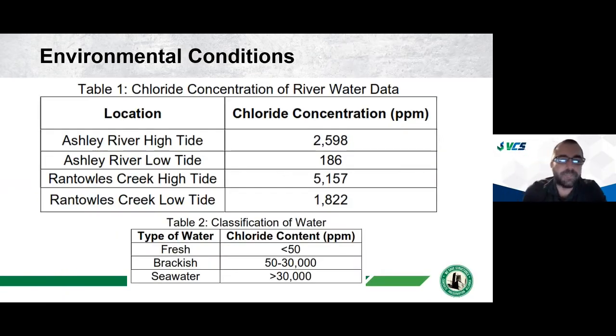And the kind of interesting part of this project is looking at the environmental conditions. So taking water samples at low and high tides, you can really see the effect of the backwash of the salt water up into these creeks. Ashley River at high tide, we can see a chloride concentration of 2,500, but at low tide, it drops to 186. And so you can see there's a very significant saltwater change every day with the tides.